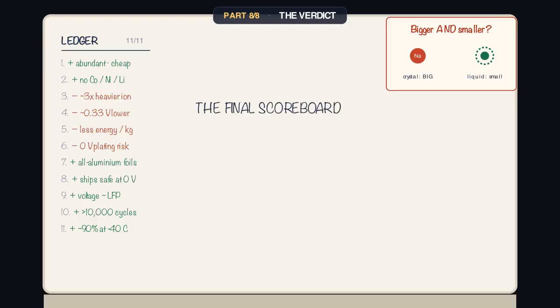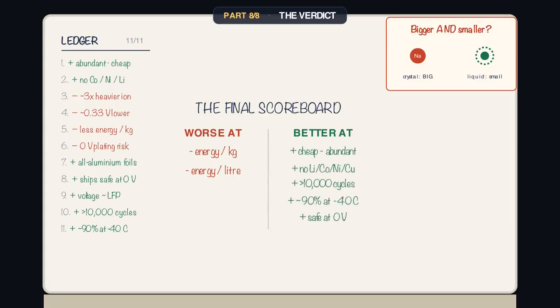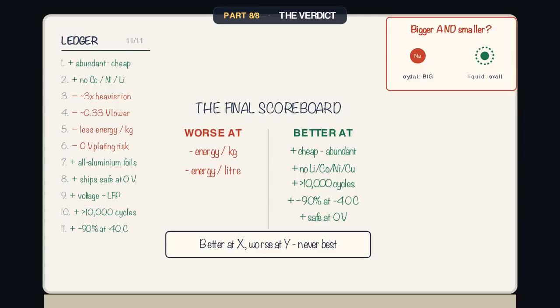So read the final scoreboard and read it honestly, because we earned every line. Sodium is worse at energy density, gravimetric and volumetric both, so it loses exactly where phones and long-range cars care most. And that's not a flaw someone hid, it's a heavier ion and a lower voltage. But look what it won. Dirt cheap, everywhere abundant sodium, no lithium, cobalt, or copper, 10,000 cycle lifetimes, safe enough to ship at 0 volts, and working in cold that stops lithium dead. Not best. Better at different things, which points it straight at grid storage, cheap city EVs, and freezing climates.